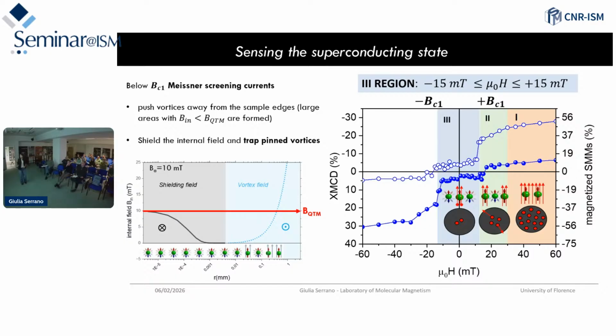This explains why our signal concerning the magnetization of the molecule doesn't really go to zero, but stays at a low magnetization value, a constant value between plus and minus Bc1. So in this case, we have a few molecules which retain their magnetization because we trapped some vortices inside.